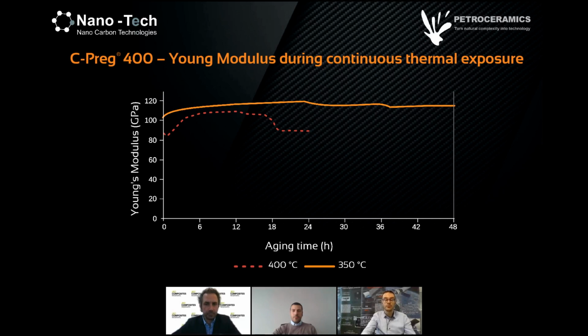is reflected also in stable mechanical properties over prolonged exposures at those temperatures. So in these images, we can see the Young's modulus that was tested during continuous thermal exposures in our DMA facility. So we exposed the samples at 350 degrees for 48 hours, so a couple of days. And we exposed the composite to 400 Celsius degrees for 24 hours. And you can see that at 350 Celsius degrees, basically the Young's modulus remains stable. And at 400 Celsius degrees, we have a slight deterioration of the Young's modulus after 18 hours, but there is no major drop of the curve.